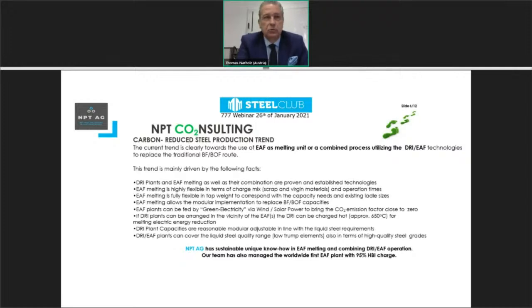EAFs, as already said in our first speech we saw today, can be fed by green electric energy via wind or solar power to bring the CO2 factor close to zero. DRI plants can be arranged either very close to the electric arc furnace to have hot DRI charging for a further decrease of the electric energy used in the production, or can be placed wherever the place is, and then cold DRI can be charged to the furnace. The DRI plant capacities are also modular, adjustable with the liquid steel requirements. And it can also cover, which is very important for existing plants, a certain liquid steel quality range, which purely with scrap is not possible to manage. So we always have to look at the final product already produced in a traditional plant. And here we have to find a way to balance the tramp elements in the liquid steel. Next slide.